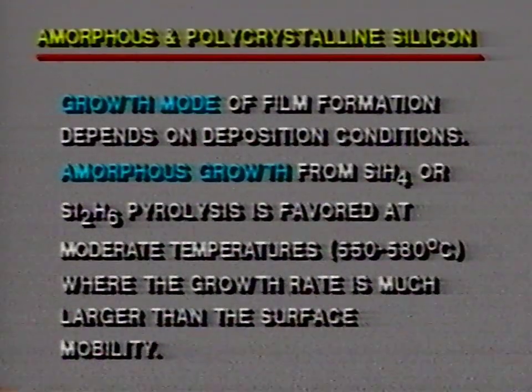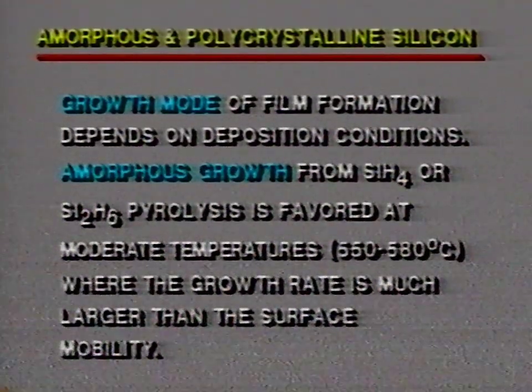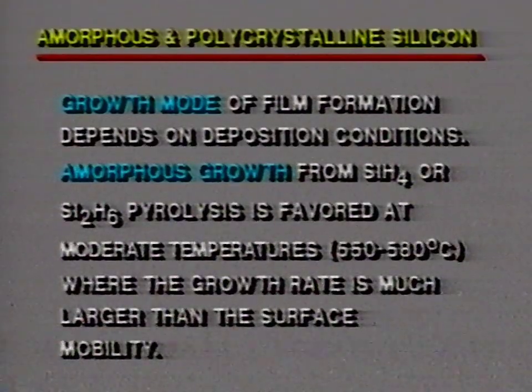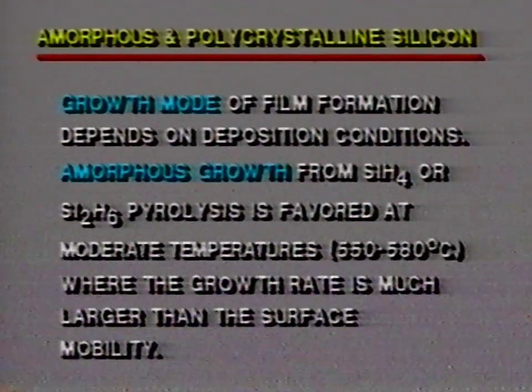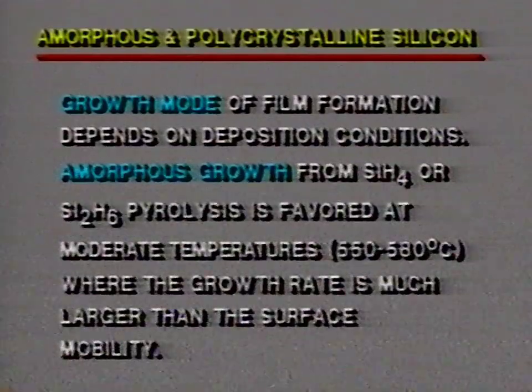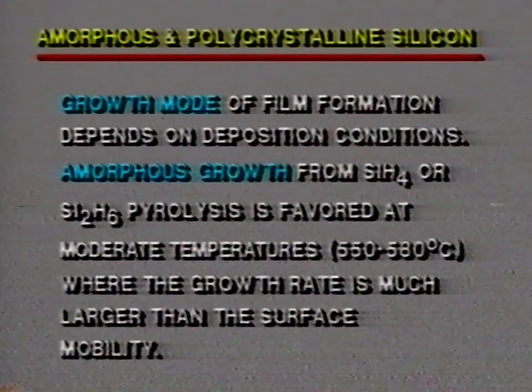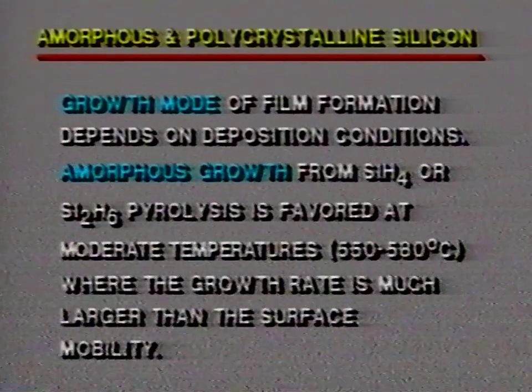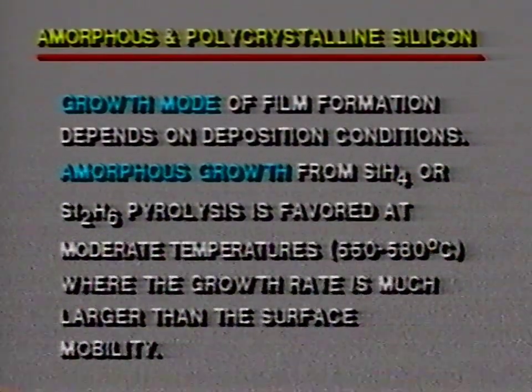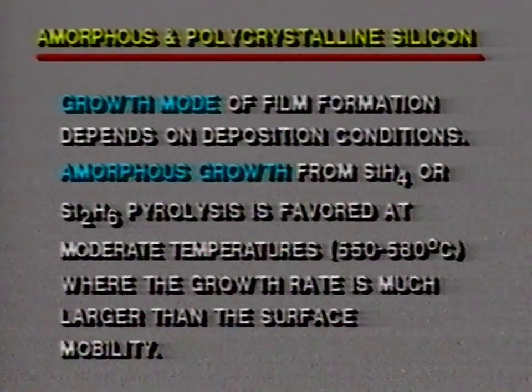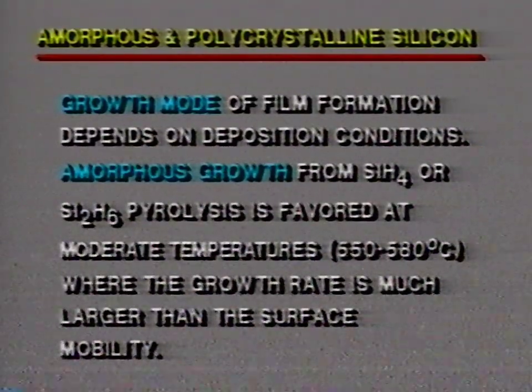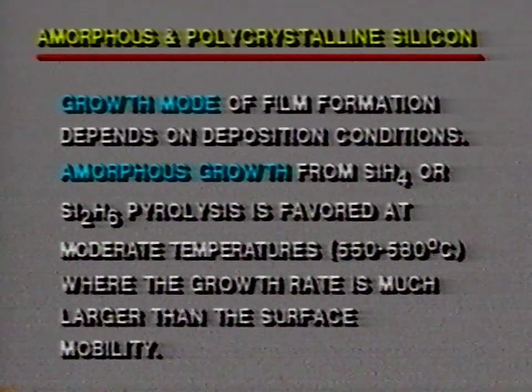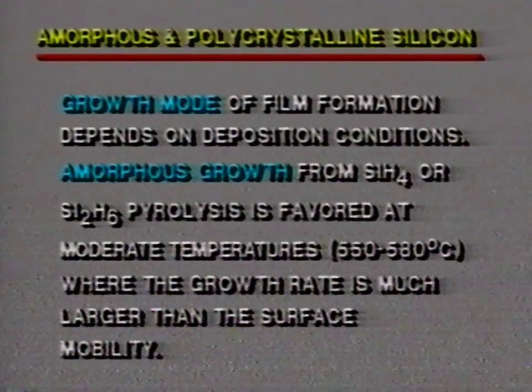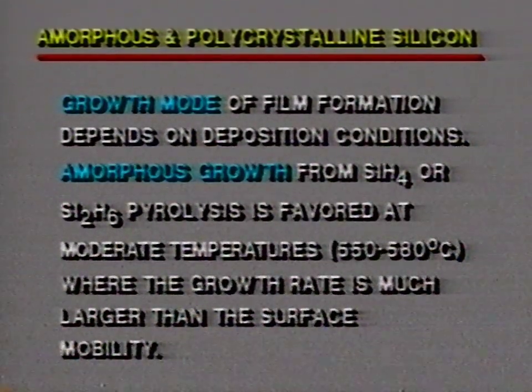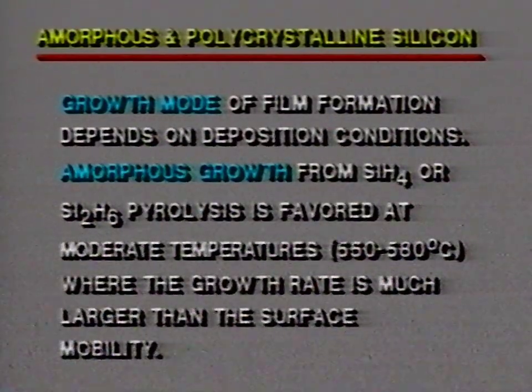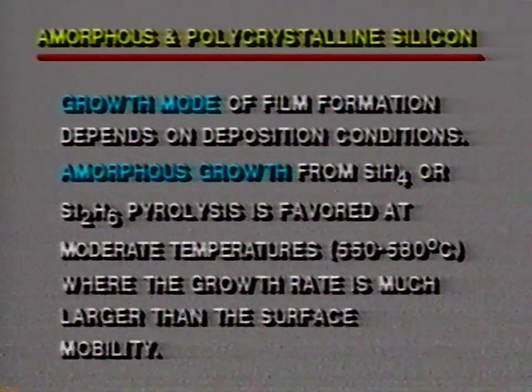I have listed the key features in each case here. The growth mode of the film formation depends very much on deposition conditions. Namely, the amorphous type of film from silane or also from disilane pyrolysis is favored generally at a moderate temperature in the range of about 550 to 580 degrees centigrade. And in this case, the film growth rate is much larger than the surface mobility of the atoms at the substrate surface. So as a result, you have an amorphous type film forming.